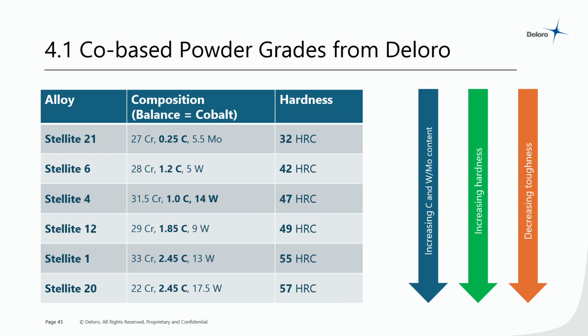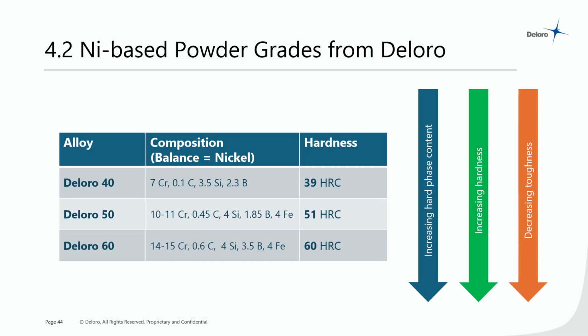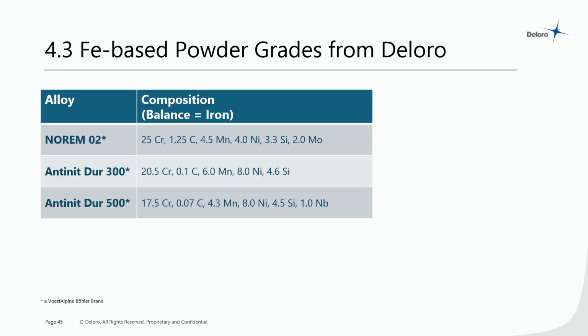We also offer nickel-based powders. I just listed the 3 most commonly known ones here, the DELORO ones. Again, different hardnesses, different hard phases. And then we have iron-based powders, which is particularly interesting for nuclear, of course. The NOREM 02, which is very well known. And then Antinit 300 and 500 are some examples of powders that can be purchased from us for HIPping or for hard facing.